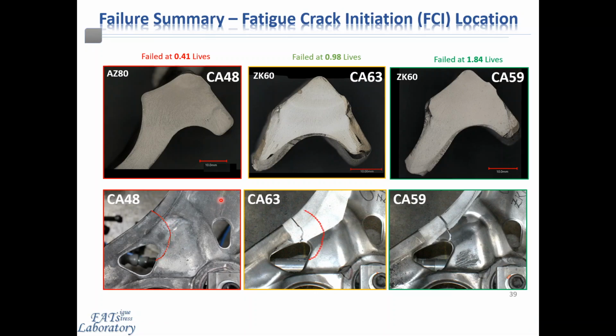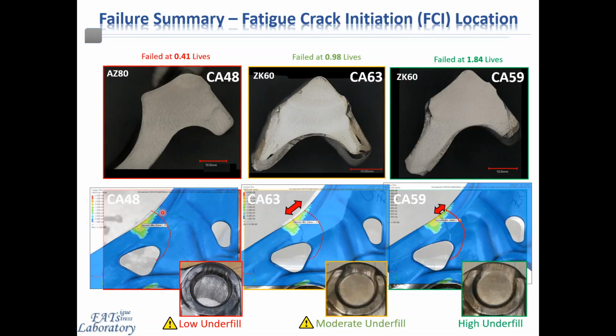If we transpose the crack path from the failure on the left to the two on the right, we can see that there's an offset of approximately 20 millimeters between them. Overlaying the fatigue life prediction from a finite element simulation, we can see that the critical location which was predicted agrees well with the two failures that are observed on the right. This indicates that those failures are due to the structural stresses governing the life of the component, and it's not a forging defect, as the finite element analysis model assumed a continuous material with no microstructural defects and homogeneous material properties.